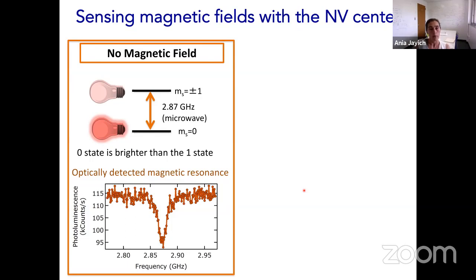So I mentioned that the ground electronic state of the NV center is a spin triplet. So there's 3 spin levels, the ms equals 0, plus and minus 1 of the spin triplet. At 0 applied magnetic field, it so happens that they're split by 2.87 gigahertz, which is easily addressable in the microwave domain.